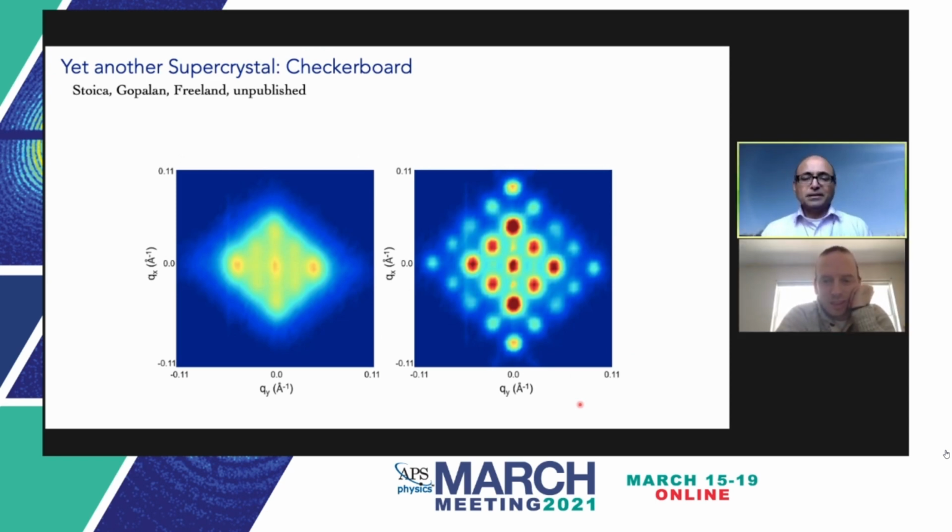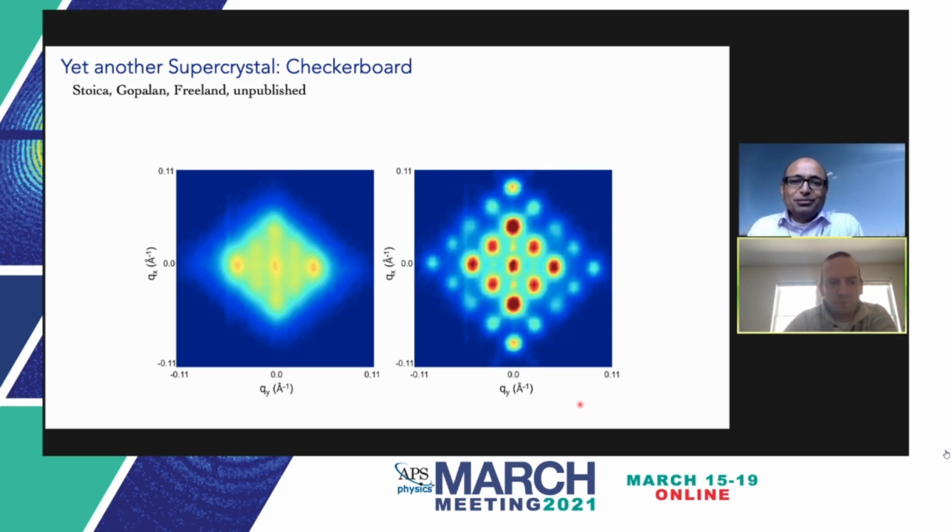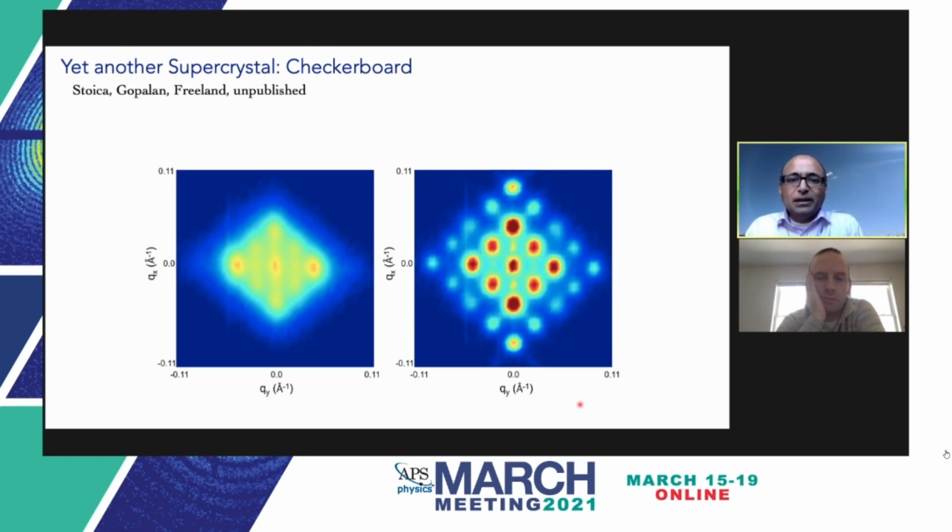Yeah, that's an excellent question. So there's a lot of systematic studies. I think this thing could go on forever. But we did do, alluding to the question about the color of light, for example, we did check that we cannot create the supercrystal if we went well below the gap. So it clearly shows that it is important. The carrier dynamics is definitely very, very important in being able to create this